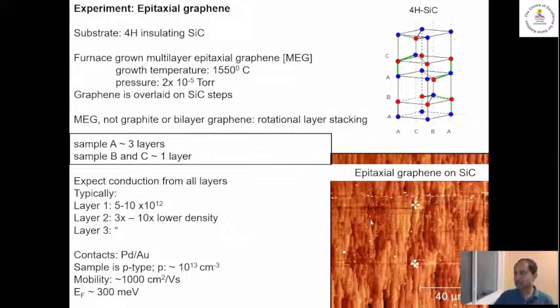So here's a picture of our epitaxial graphene on silicon carbide. Actually, what you're seeing is just the surface of silicon carbide, but it's covered with graphene, right? But you can't see it. And this is realized by heating the silicon carbide to 1500 Celsius. And then I'll be talking about results in two kinds of samples, 3-layer samples and 1-layer samples. So these are p-type samples with holes in the range of 10 to the 13 per square centimeter. Mobility is like 1,000 centimeters squared per volt second. Fermi energy is like 300 meV in the valence band, right?